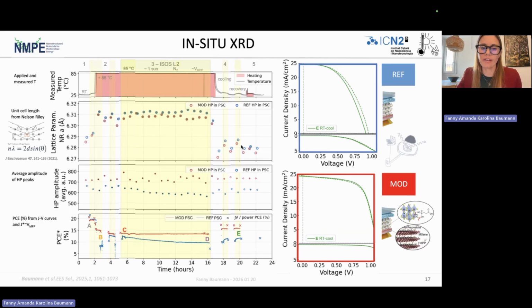So we can really also conclude here that the inner temperature of the perovskite layer is likely quite a bit higher than the temperature that we have if we're only heating at lower temperatures. At 85 degrees, well, this was pretty stable.